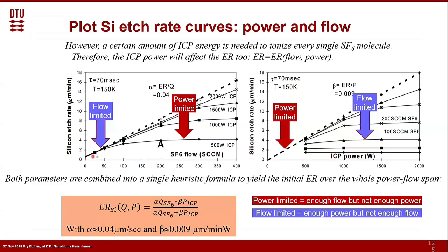Now, looking at these two curves, these two slopes, this one means silicon etch rate divided by the flow. We call this one alpha. It's etch rate divided by flow, and if you take that curve, it's around 0.04 micrometers per standard cubic centimeter. We can do the same for this curve, and this one gives us something like 0.009 micrometers per minute per watt, or 9 nanometers per minute per watt.